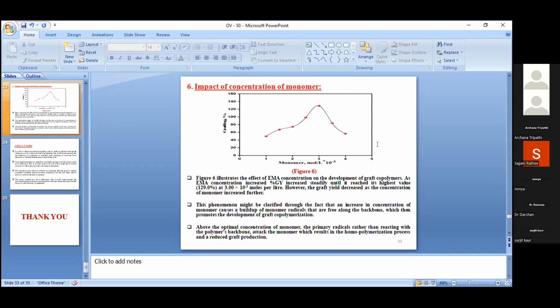Last one is impact of concentration of monomer. Figure 6 illustrates the effect of EMA concentration on the development of graft copolymer. As the EMA concentration increased, the percent graft increased steadily until it reached a higher value, that is 129% at 3.00 x 10^-3 moles per liter. The graft yield decreases as the concentration of monomer increases further.